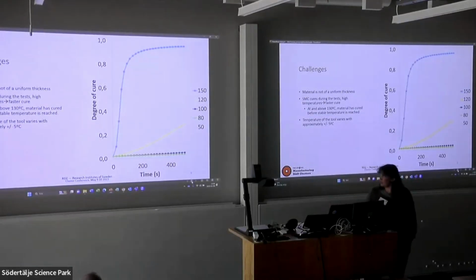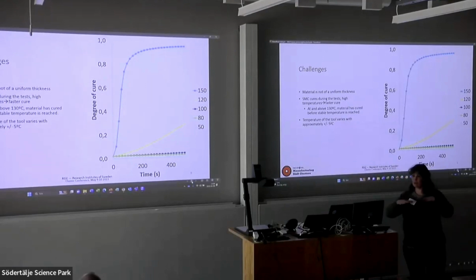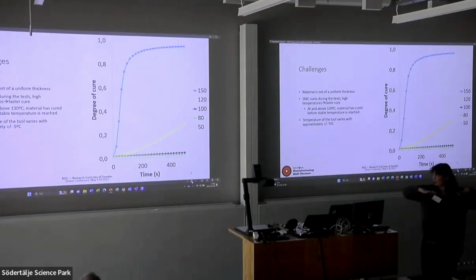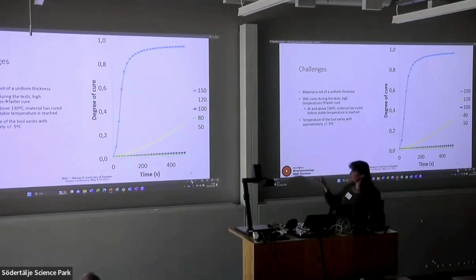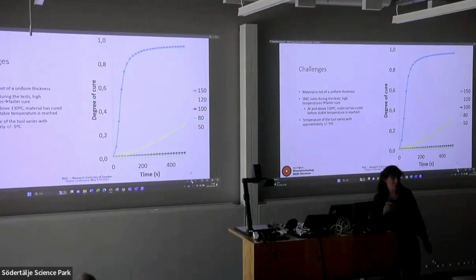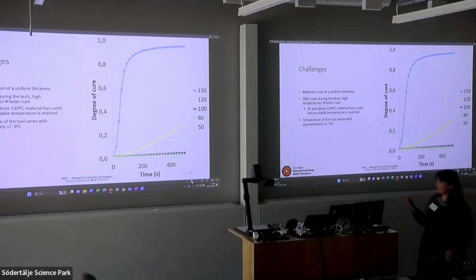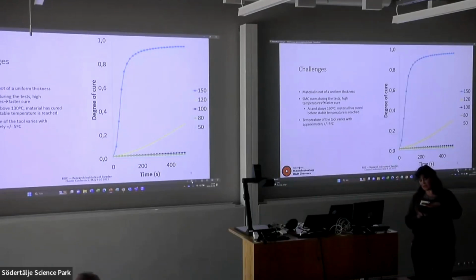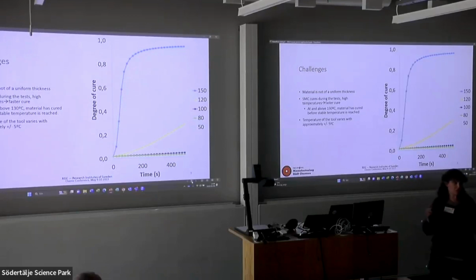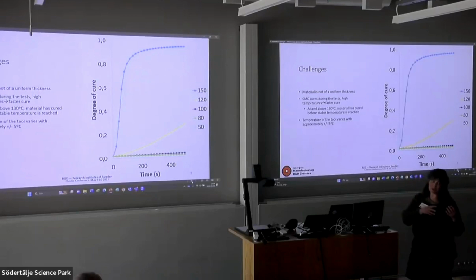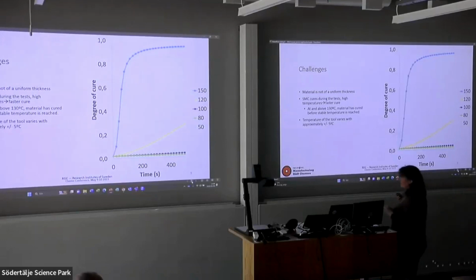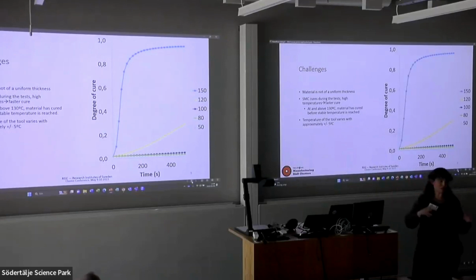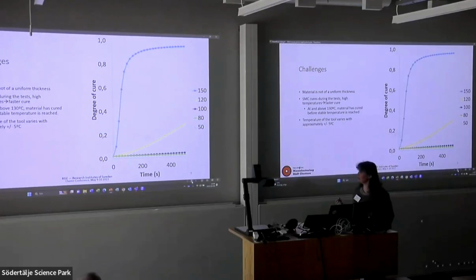So some of the challenges: the material itself is not uniform. They spend a lot of time trying to make the orientation of the fibers quite nice and even, however, the thickness does vary along the sides. So that makes it difficult to characterize. The SMC cures during the test, particularly at high temperatures, so after 130 degrees, we don't have enough time for the whole piece of the material to be at 130 degrees before it starts to cure. So we basically have to try and characterize it at lower temperatures and try and predict how it's going to behave. And this is the Kamal's model that we're trying to use to fit. This isn't particularly an issue for when it's manufactured, but it is an issue for characterizing. Has to be a bit careful. We also have a slight problem with the tool temperature, which varies approximately plus or minus 5 degrees.